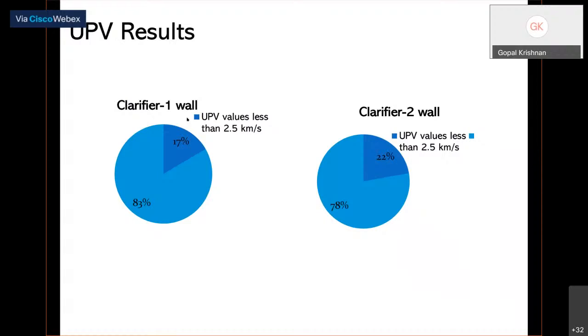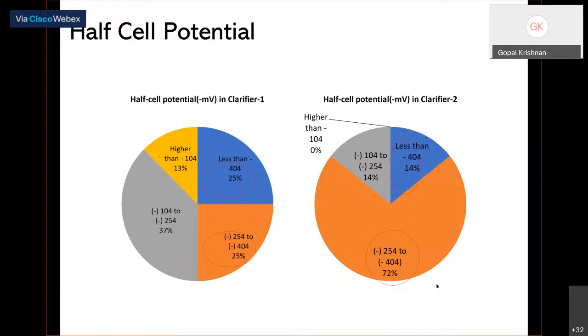Then we can see the UPV value is satisfactory in the clarifier: the majority, 78% to 83%, was found satisfactory. And then the half-cell potential, if you see how much here: 86% is severe, only 14% lower. That means it is high corrosion. And the clarifier one, how much? 50% probability of corrosion severity and 50% lower probability.